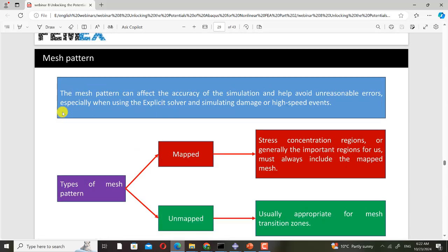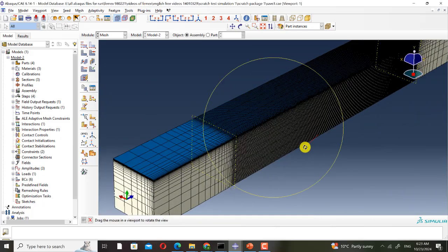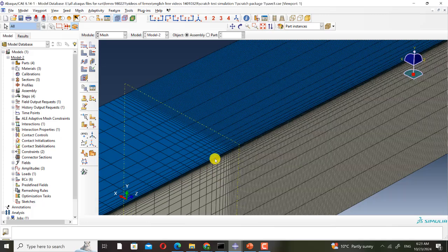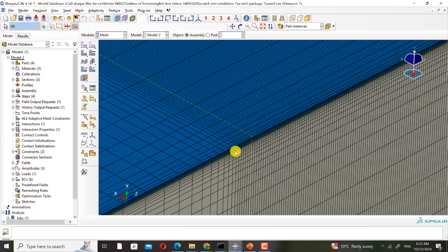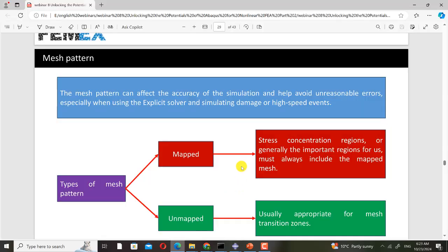Now I want to talk about the mesh pattern. The mesh pattern can affect the accuracy of the simulation and help avoid unreasonable errors, especially when using the explicit solver and simulating damage or high speed events. We have two types of mesh patterns, mapped and unmapped. For mapped, actually we must use mapped mesh in the stress concentration regions, or generally the important regions for us. For example, here, in all of the regions, okay, in all of the regions, I have used mapped mesh, okay? Because according to my experience here, it was good to use the mapped mesh. And also we have unmapped mesh, and it is usually appropriate for mesh transition zones. What is mesh transition zones? For example, you have large element in one side and a small element in the other side.